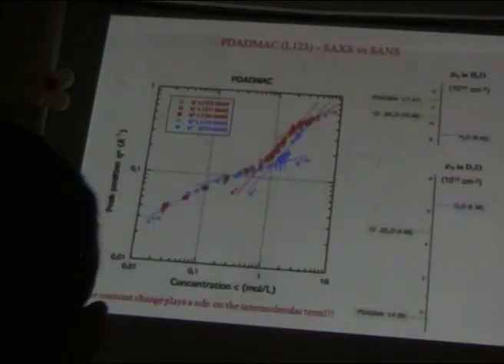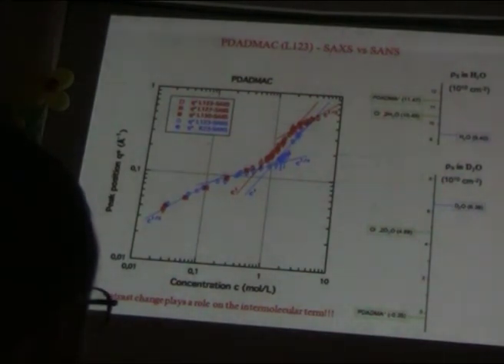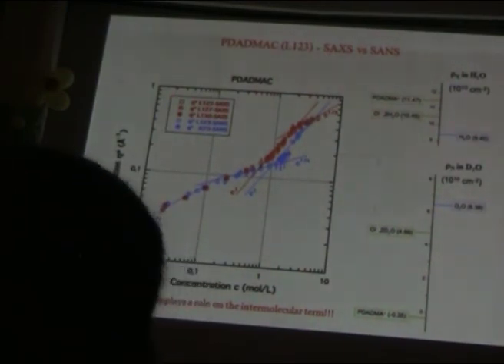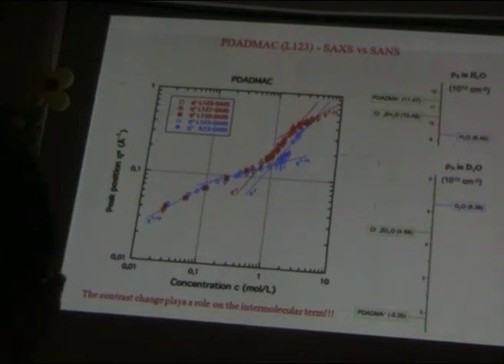I finish in 1 minute, sorry. Here, there is a comparison between results obtained by small angle X-ray scattering and results obtained by small angle neutron scattering. It's quite interesting because, to my knowledge, it is the first time that I see the influence of the labeling of the contrast on the intermolecular term, not on the intramolecular term. Usually the effect is on the intramolecular term. But here it's an effect on the intermolecular term. And it's only related to the fact that the counterions are much more mobile along the polymers. And when you consider the counterions, of course, the excluded volume is reduced. So the position of the maximum is not at the same position as if you look at only the macroions. Okay?